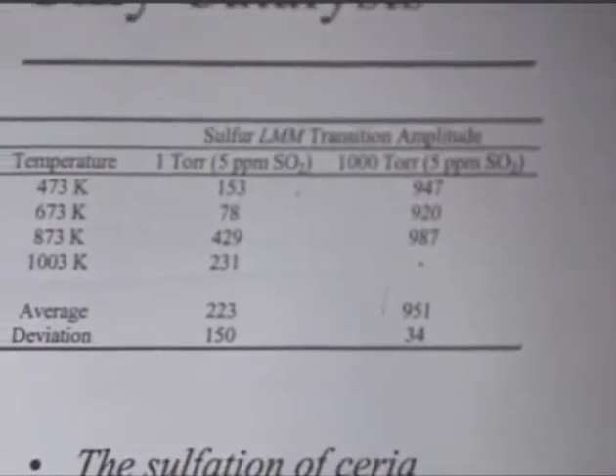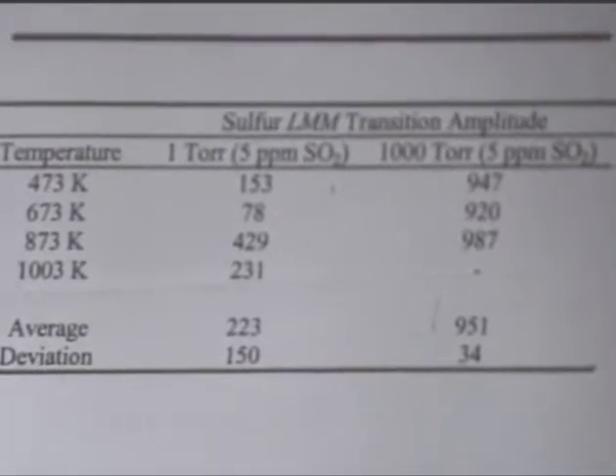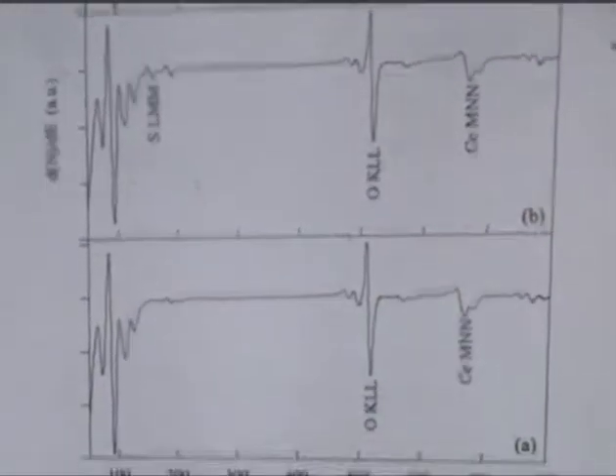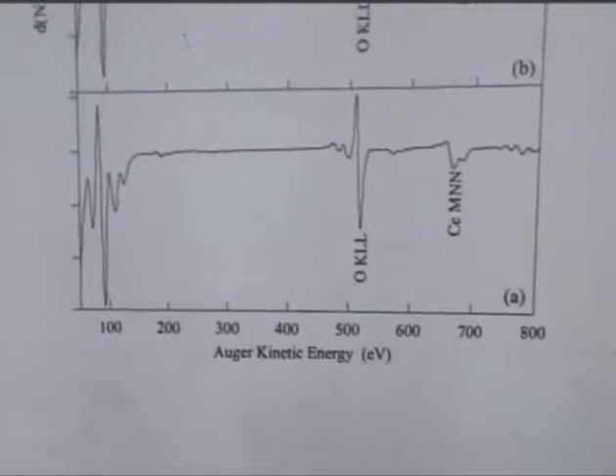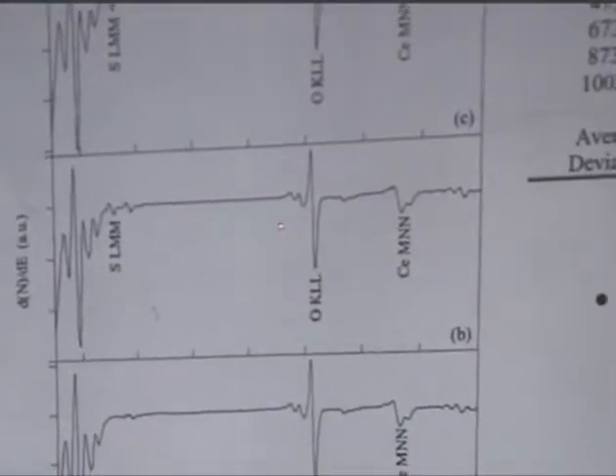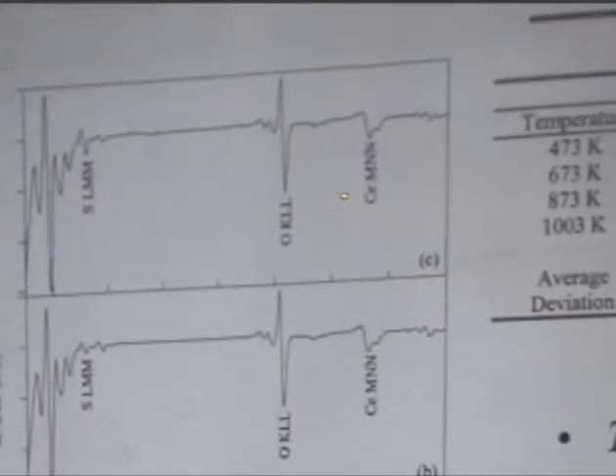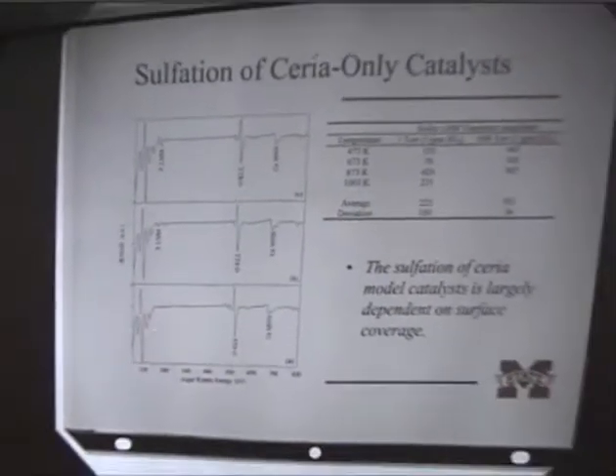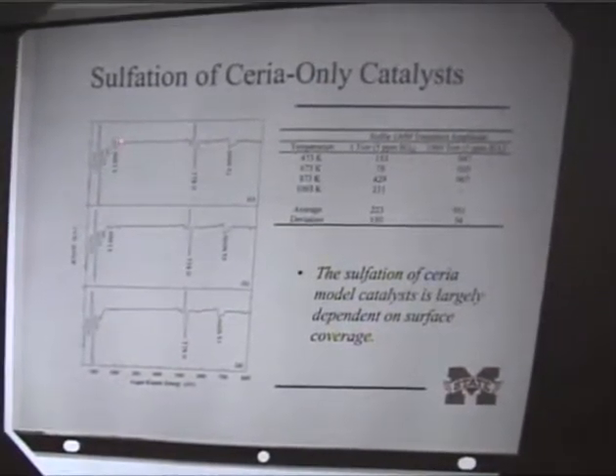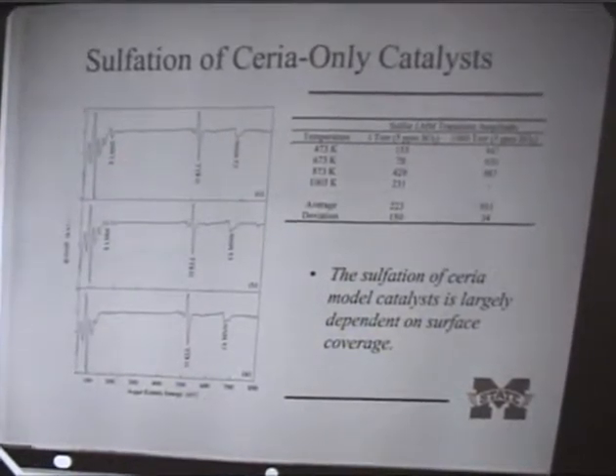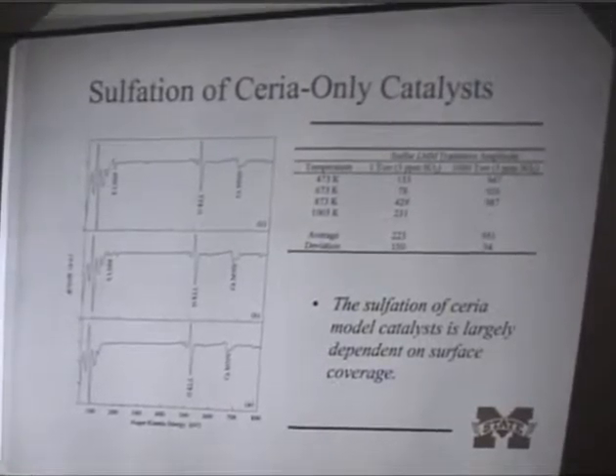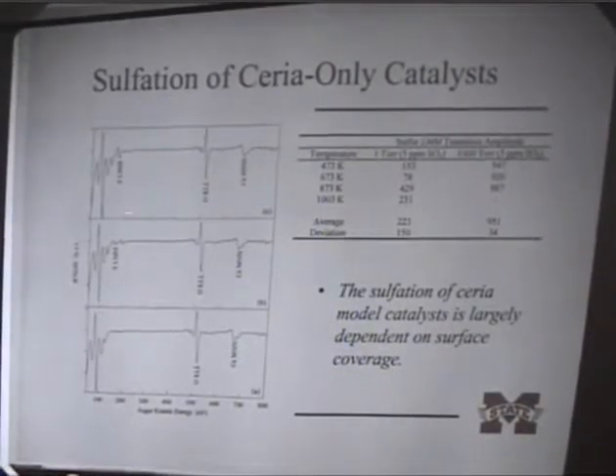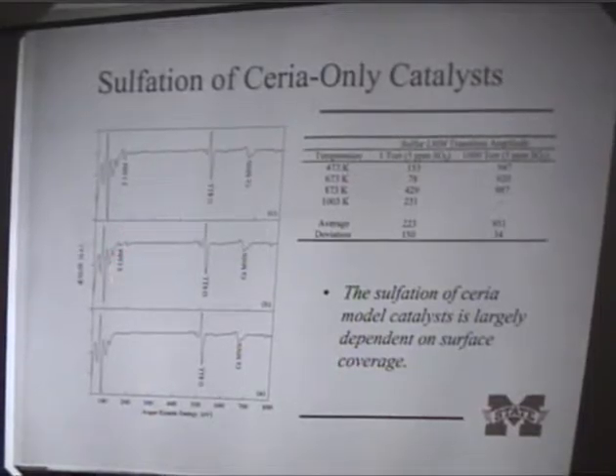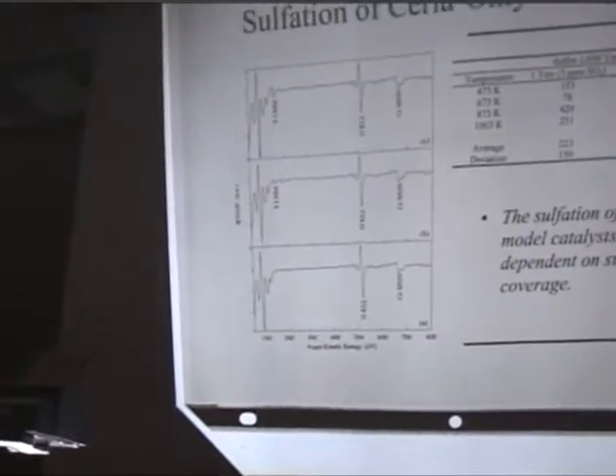So sulfation of the ceria only, this is what we started with. What's shown here are some Auger results. This is the 100% ceria. This is the clean sample. This is the lower pressure exposure. This is the higher pressure exposure. And what's shown here is I was just illustrating where the sulfur tends to grow in. If life were easy, everybody would do these things. The problem is cerium transitions occur directly over the top of sulfur.